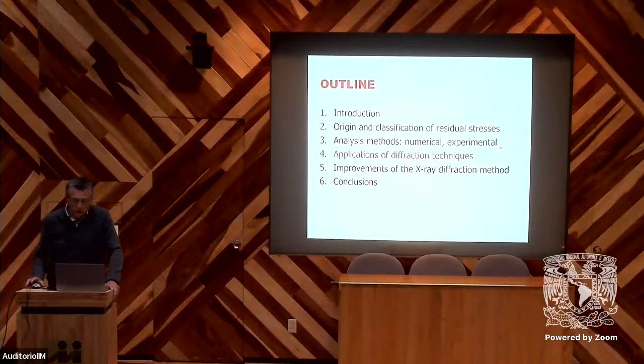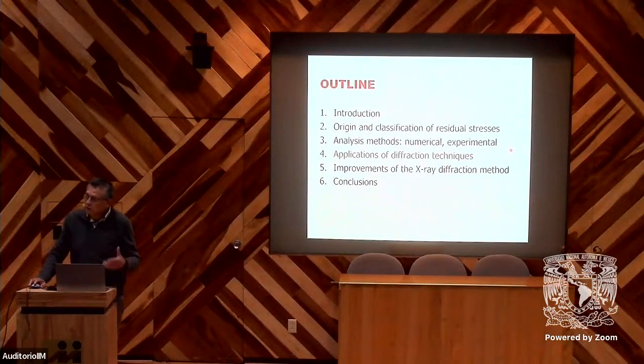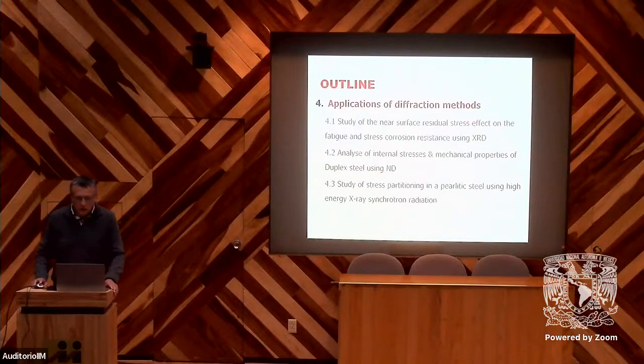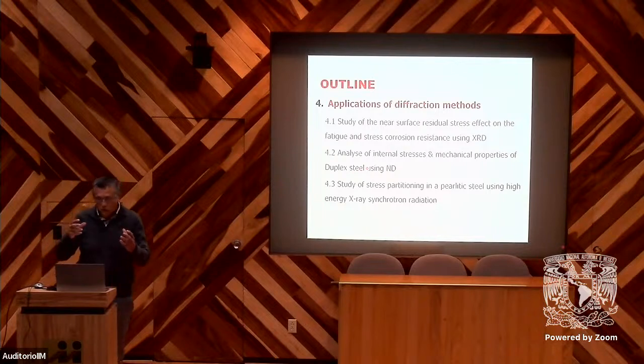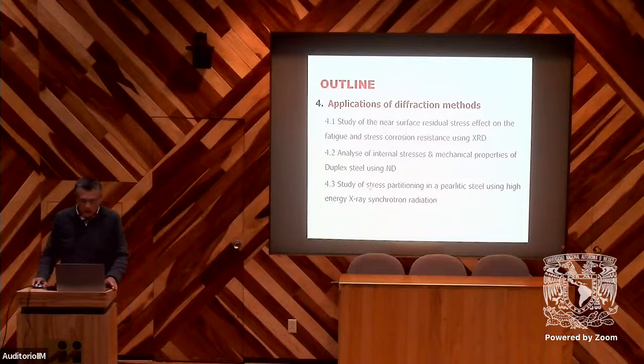Now let's see some studies using these diffraction methods. And for this, I will present first a study using X-ray diffraction to study the effect of residual stresses on fatigue and on stress corrosion cracking. And then I will present a study using neutron diffraction to study a multi-phase material, this duplex stainless steel. That means we use this method to study the behavior of the different phases. And the third example is a case using synchrotron radiation.